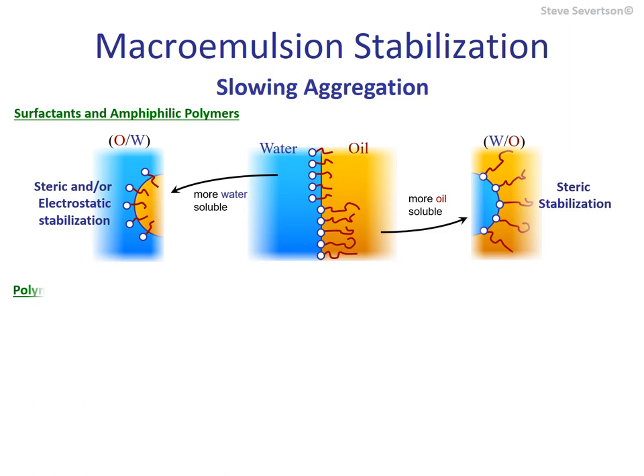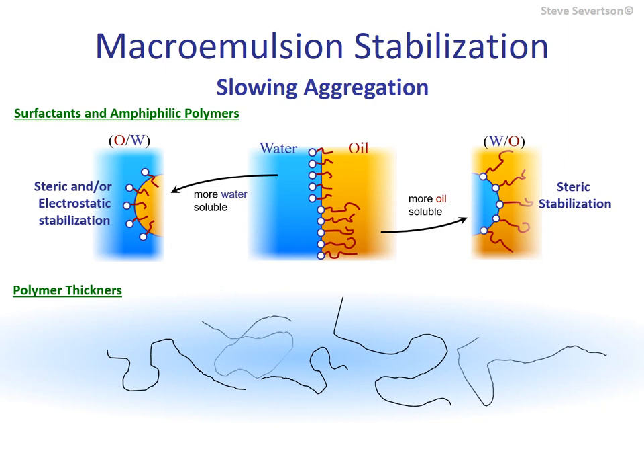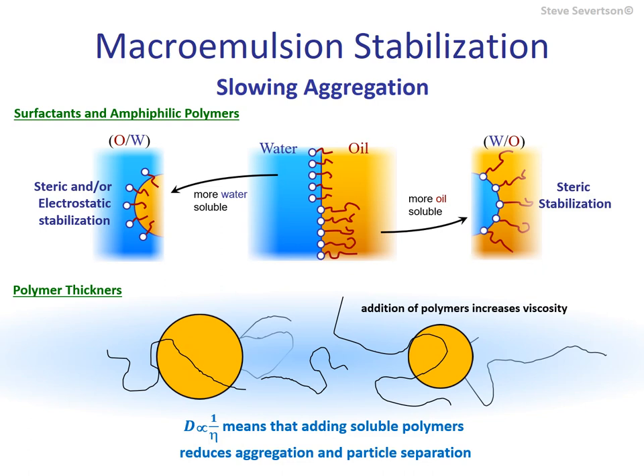In some products where increasing viscosity is not an issue, polymeric additives can be used to increase the viscosity of the continuous phase. Particle diffusion is inversely related to viscosity, so the use of polymers to thicken the continuous phase helps stabilize the particles against creaming and sedimentation, and also slows other particle growth mechanisms to increase the overall kinetic stability of an emulsion. Coalescence requires that interfaces be brought together to rupture, eliminating the interface between particles and allowing particle components to intermix. The rate of this process is largely controlled by the mechanical strength of the interface, so additives that reinforce this region will slow coalescence.